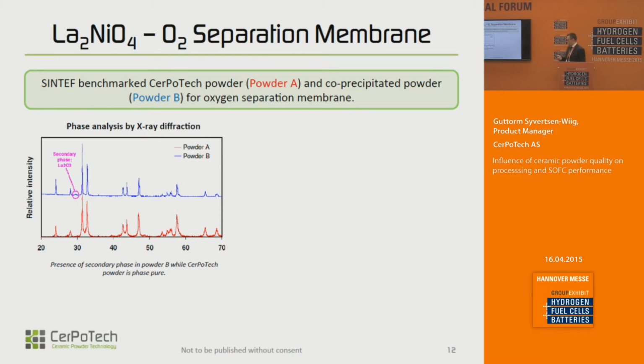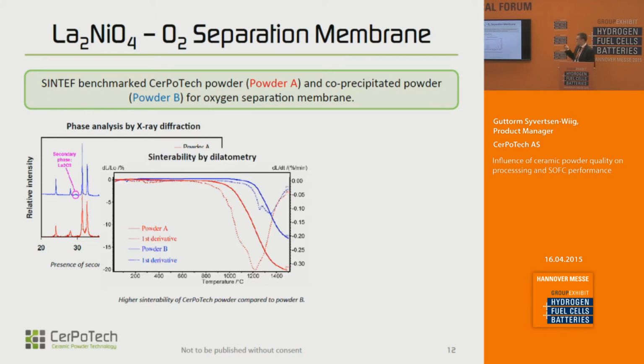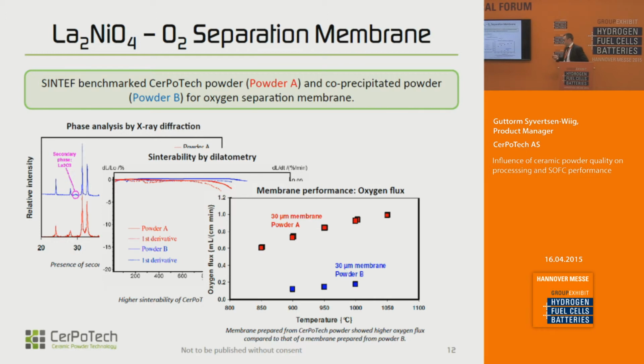So here is an example for an oxygen separation membrane, a benchmark test done by SINTEF Technology Institute in Norway, where the CerPoTech powder is the red powder, and you have some co-precipitated powders from another powder supplier in blue. First, the phase purity is higher for the spray pyrolyzed powders compared to the other one. This has an effect on both properties and sintering behavior and so on. As you can see here, you can actually reduce the sintering temperature by up to 200 degrees for the spray pyrolyzed powders compared to the co-precipitated powders. And all this again gives quite a large effect on the actual oxygen ion transport through the membrane.